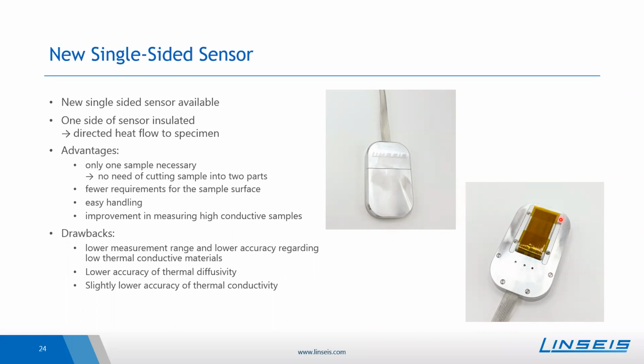Additionally, one has fewer requirements for the sample surface, because for the two-sample setup you need two sample pieces which fit perfectly on top of each other so that there's no air. Here you have only the requirement of one straight, smooth surface where the sensor can be put on top. It is also easy in handling, and especially for highly conductive samples, such as metals, it shows an improvement in measurement.